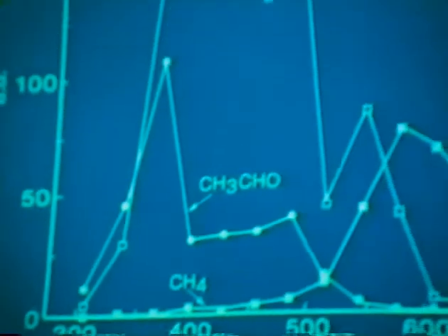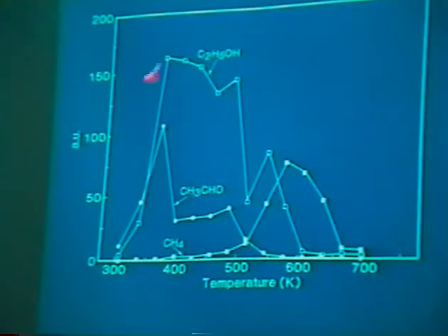On the hydrocarbon synthesis catalyst, you may find the same products, although in this case you have a catalyst which is pretty selective towards hydrocarbons. So what you find is only acetaldehyde, ethanol through hydrogenation, and only methane at high temperature, no formation of acetone. Of course, here we have also CO and CO2 formation, which was not mentioned on this plot.